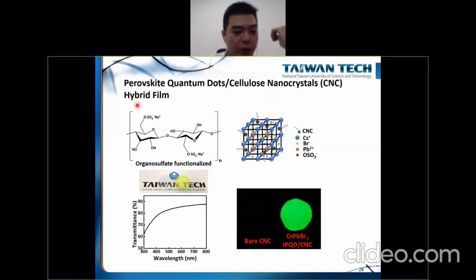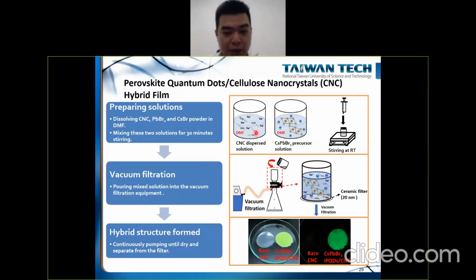We use sulfate-functionalized cellulose nanocrystals, and unlike traditional capping ligands, we mix the CNC dispersed solution with our quantum dot precursor, and we stir it at room temperature. And then we pour it into a vacuum filtration device. So we can come up directly with the film after this vacuum filtration process, and we put it in the oven at around 50 to 60 degrees, and it will be directly dried. And once it is dried, you can see the perovskite quantum dots, and under UV light you can see this green emission coming out from the hybrid film.